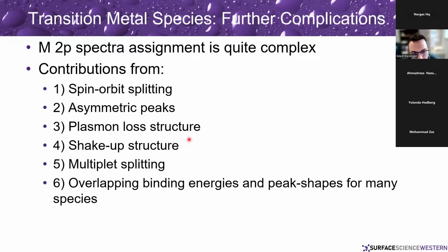All right, as we get into higher orbitals, so the 2Ps, the 3Ds, the 4Fs, and things like that, things can start getting a lot more complicated. And in particular, the transition metal species show a lot of further complications. So the metal 2P spectra from transition metals, you can get contributions from spin orbit splitting. You can get asymmetric peak shapes, plasmon loss structure. You can get shake-up structure and things called multiplet splitting. And generally, you have a lot of overlapping binding energies and peak shapes for many of the elements present.